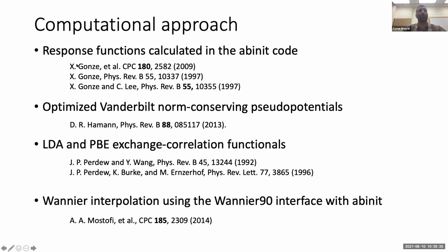Also, I'll flash up the computational approach that we used for these calculations. Our response functions and ground state properties were calculated in the Abinit code. We used ONCV pseudopotentials, both LDA and PBE exchange-correlation functionals, depending on the material. A lot of the quantities here require very fine integration over the Fermi surface, and for that we use the Wannier90 interface with Abinit to do some Wannier interpolation of the quantities in our calculation.